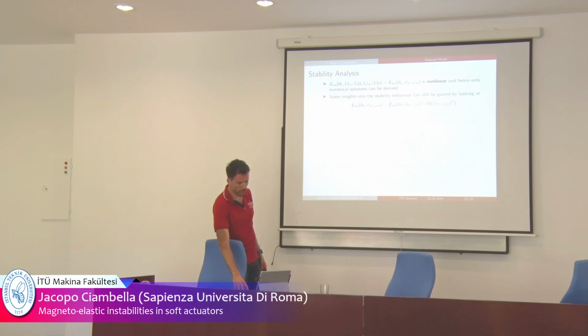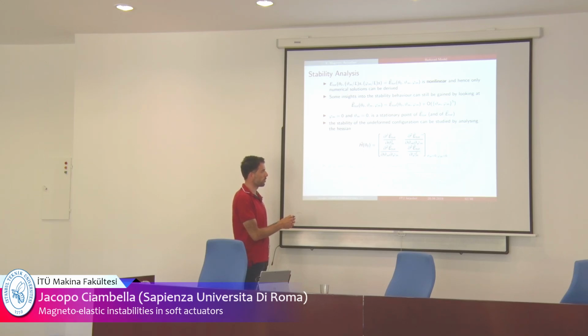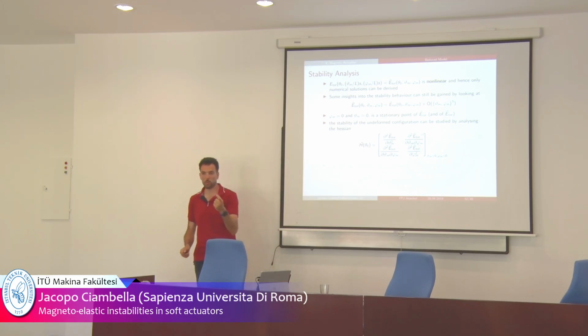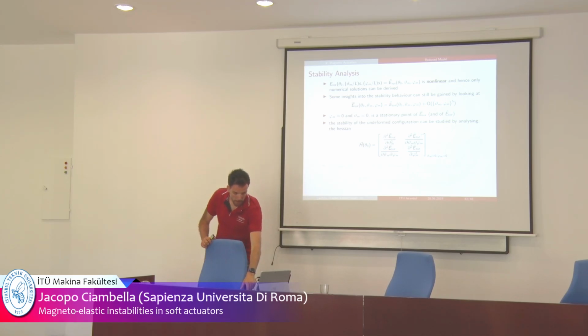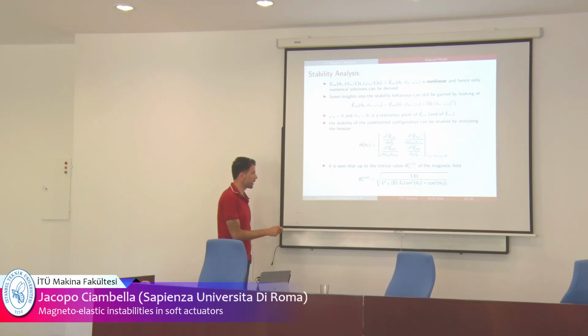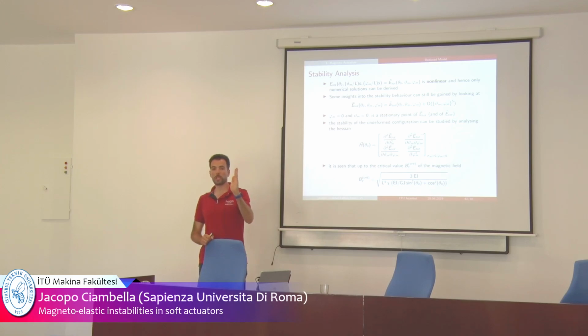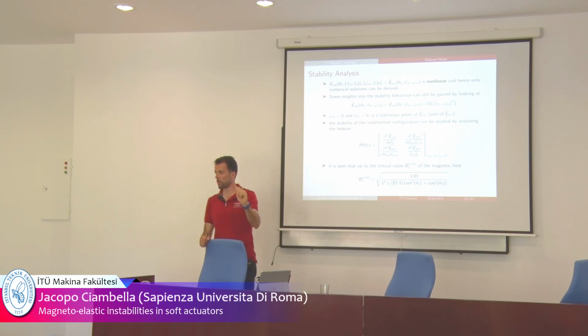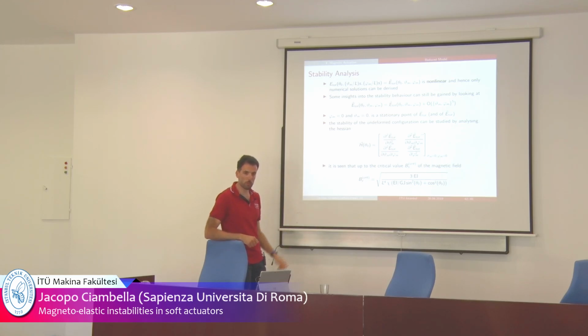You can do nonlinear analysis, and then you can approximate the energy at the fourth order, because we want to study stability. And once you have that, you can study the stability of the solution by looking at the Hessian of the energy, so whether the energy is convex or non-convex. And the nice thing about this simple one-dimensional model is that you can work out the critical field at which you have instability. I didn't say that explicitly, but that behavior we've seen before was an instability. So the specimen remained still up to a certain critical value of the field when you had a snap, an immediate deformation. With these very few equations, you can work out the critical field in closed form.